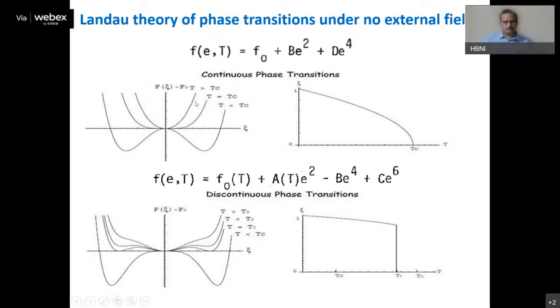This curve corresponds to the Landau free energy when the temperature is higher than Tc, and this curve corresponds to the temperature equal to Tc, where you see a lot of order parameter values become accessible, so there are a lot of fluctuations. As soon as the temperature decreases below Tc, you start getting a minima in the free energy at some order parameter value not equal to 0. This is a clear-cut indication of the continuous phase transition or second order phase transition. And you can see in this plot of order parameter versus temperature that the order parameter gradually increases from 0 to some finite value as the temperature goes down.